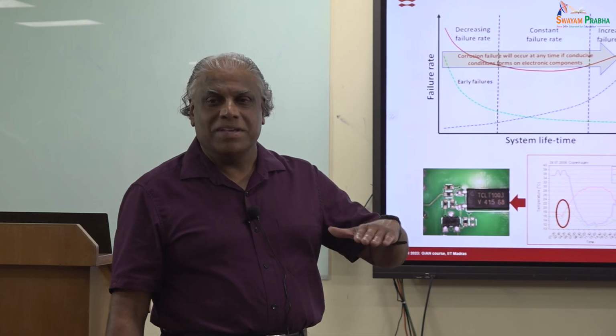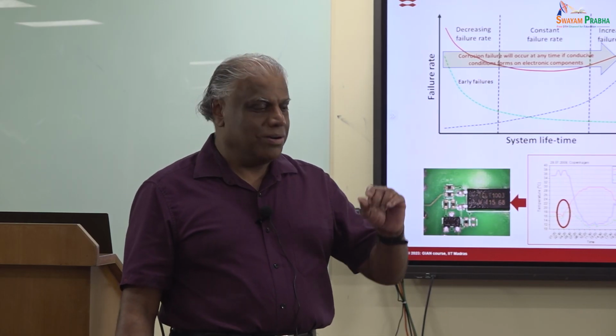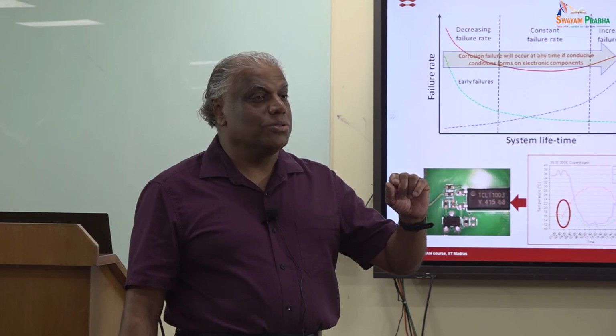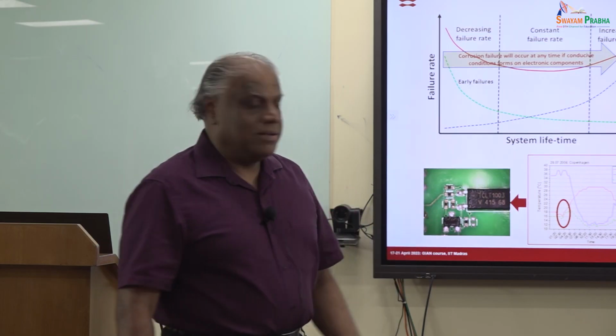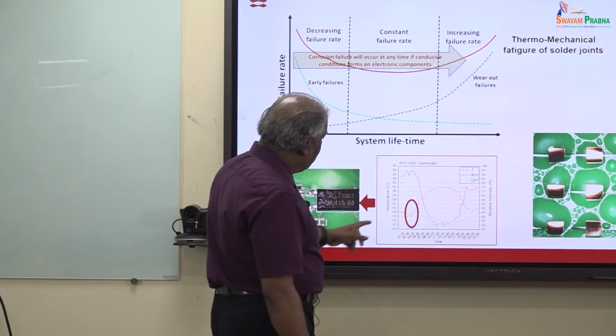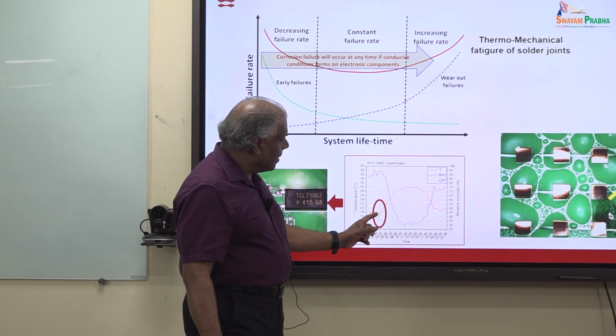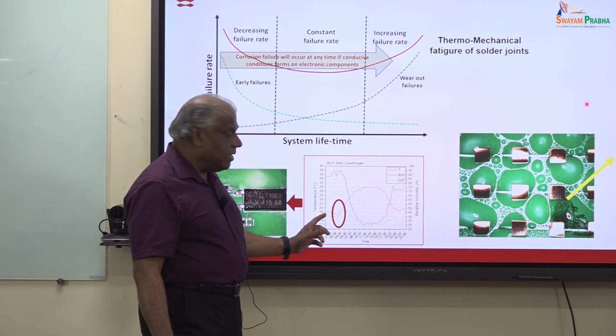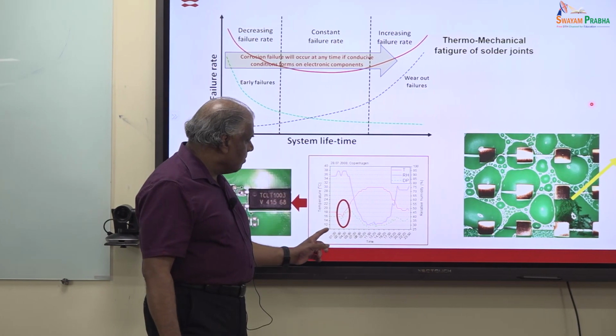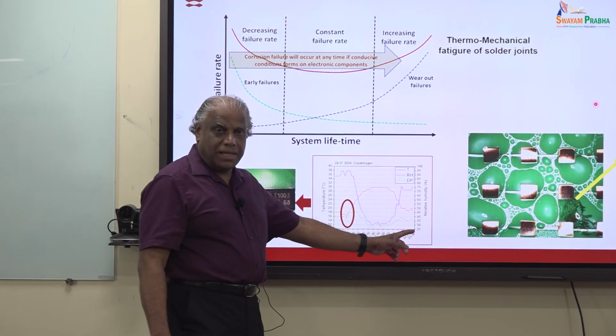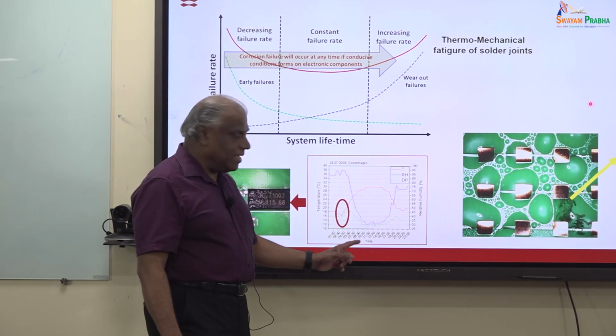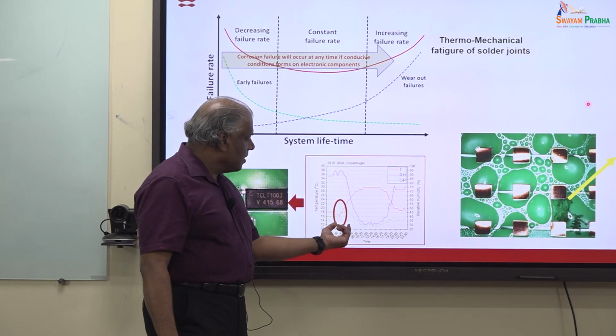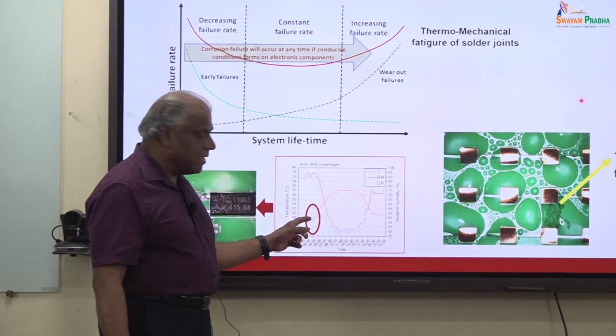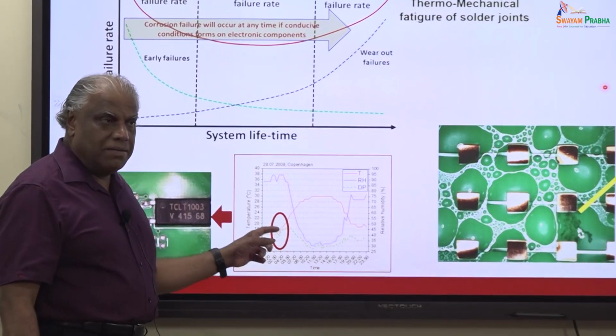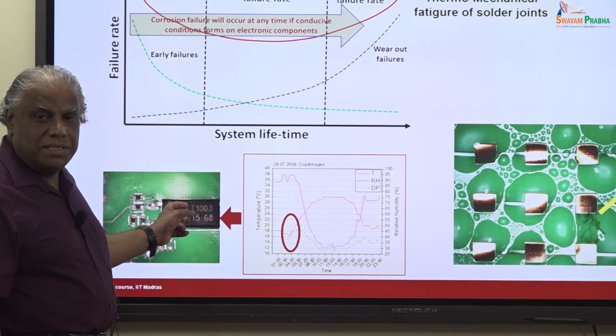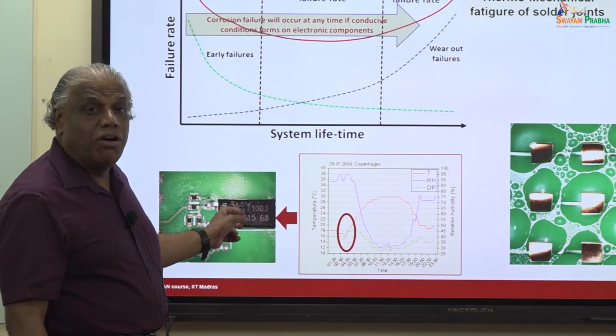That's what it means. Or we can say the condensation chances are more if the dew point temperature is close to the ambient temperature. So if you look at this profile, you can see that this is a period at which the dew point temperature is close to the temperature. In this day profile, from 12 o'clock to 12 o'clock in the night, means midnight to midnight, there is around a 2 hour period in the early morning where the dew point and this temperature are close. That's the time you have a chance to get condensation in the PCB if the electronic system is off.